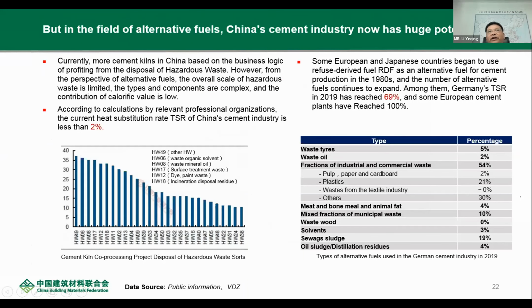Currently, alternative fuel is more and more used in China. The biggest alternative fuel ratio, at Huaxin Cement, achieved 30%. However, the national average ratio is not so high, only 2%. The highest alternative fuel ratios are in developed countries in Europe and Northwest Europe. Some countries can achieve 70%. This is an important direction for Chinese cement companies to work toward.